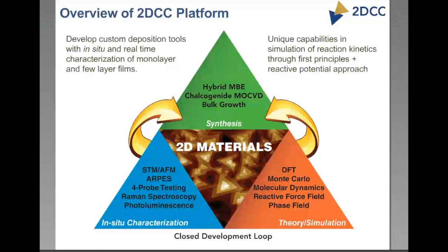So the overview of the 2DCC platform is shown in this plot here. It's a combination of doing synthesis, hybrid MBE, chalcogenide MOCVD, and bulk growth, and that forms the basis of what we do. And then we fold into this characterization, which is in situ. So for example, STM, ARPES, and 4-probe measurements of electrical properties, as well as Raman spectroscopy and photoluminescence.